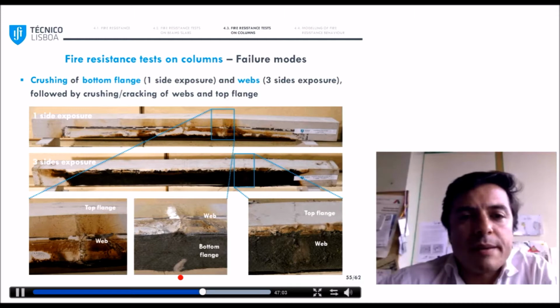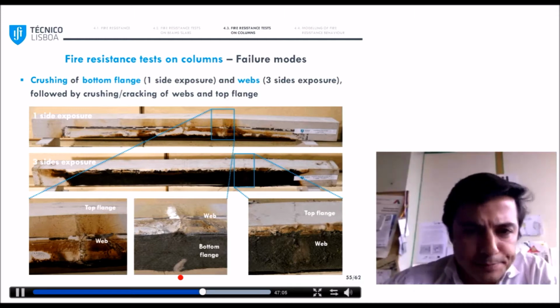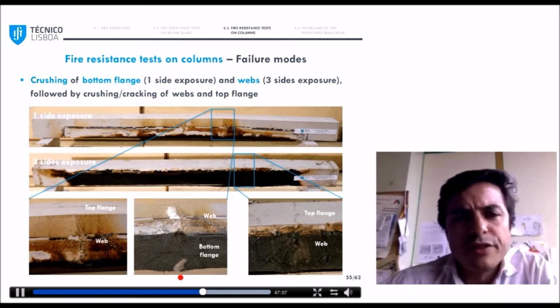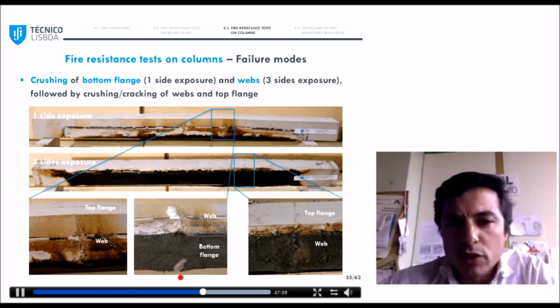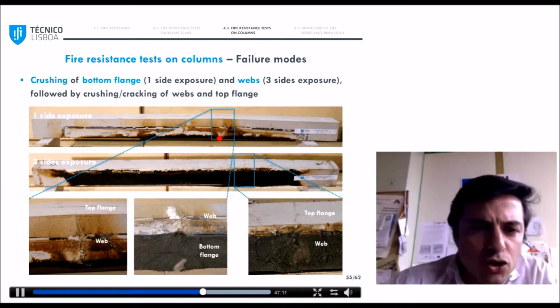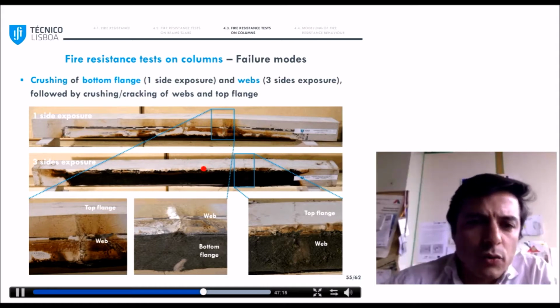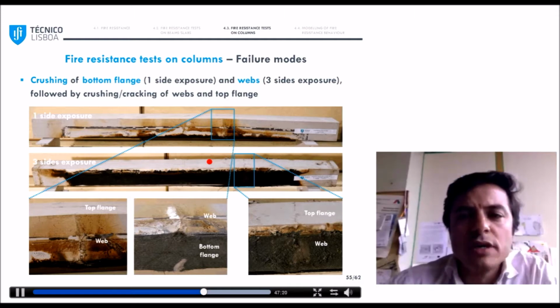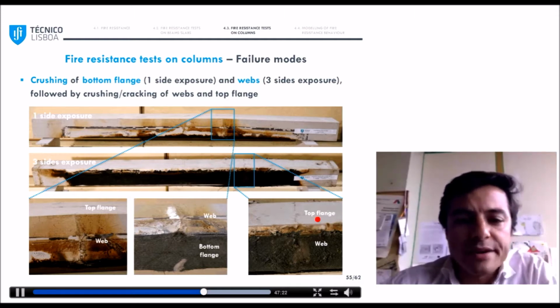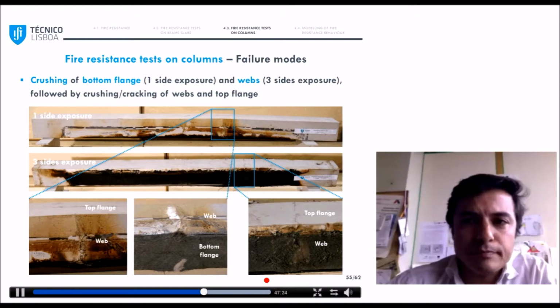So collapse was always caused by the crushing of the hottest walls: the bottom flange for one side exposure that you see here in the top, and also the webs that you see here in the middle for three side exposure, which was followed by the failure of the remaining walls.